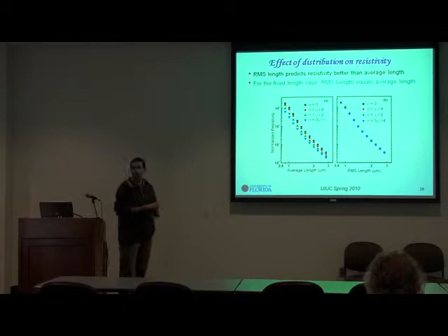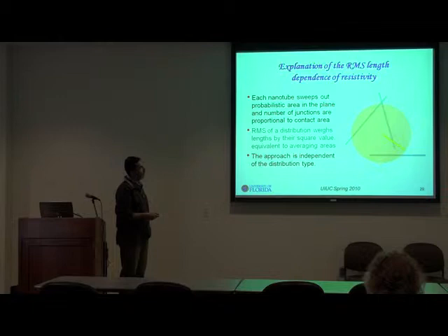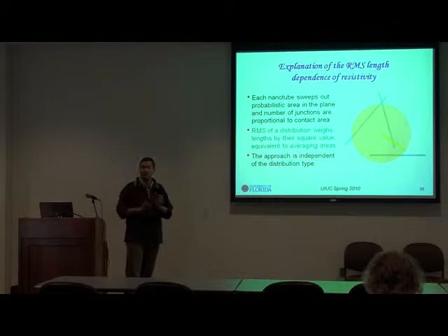And the reason we found out that this second power of length is important was that when you change the length of the nanotube, each nanotube sweeps an area like this circle around the nanotube that you see. So it's related to the second power, the area of that circle depends on the second power of the tube length. So it's important that you know what parameter is the important parameter for scaling. In this case, it was the length to the power of two.